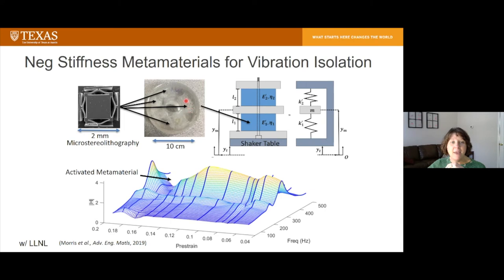And then they basically strain the surrounding matrix and provide energy dissipation. So in this plot down here in the bottom, you can see frequency on this axis, and you can see that there is a resonant frequency for this structure, this ridge that you see here. And you can also see that at a particular level of pre-strain, when we activate these elements, they're almost ready to snap through, we basically eliminate that resonance peak. And we get broadband damping from this structure.